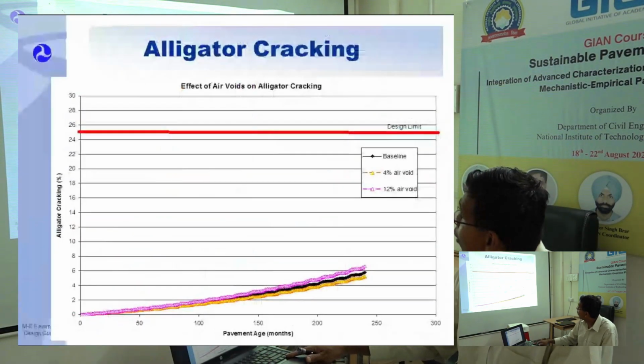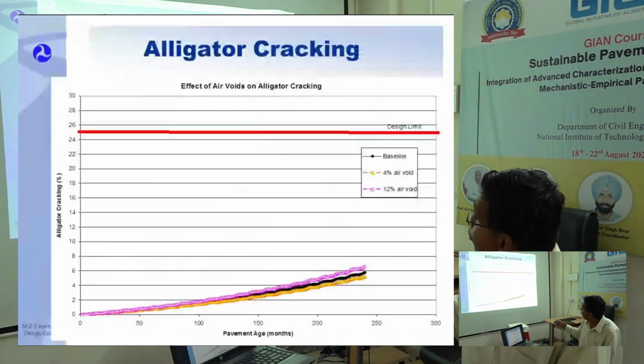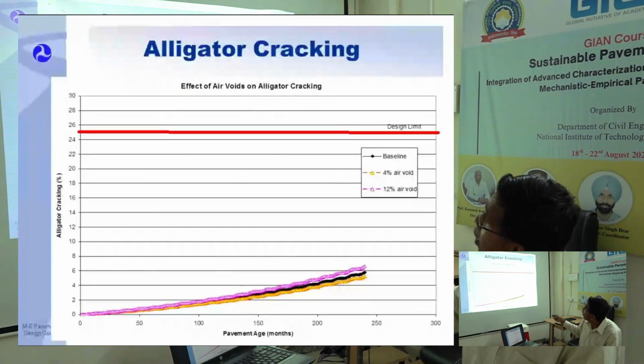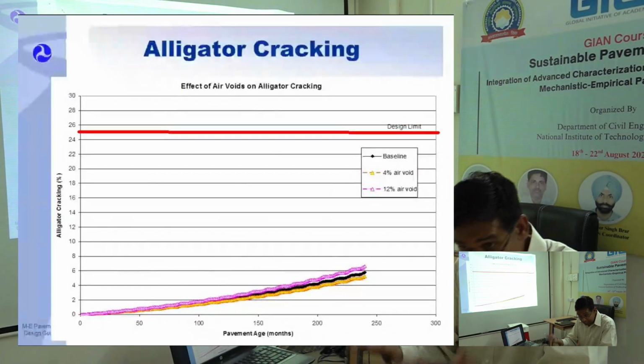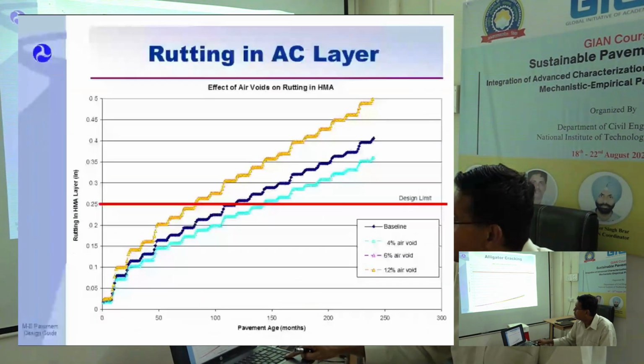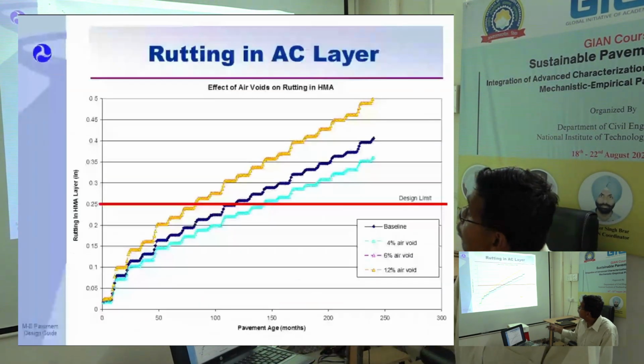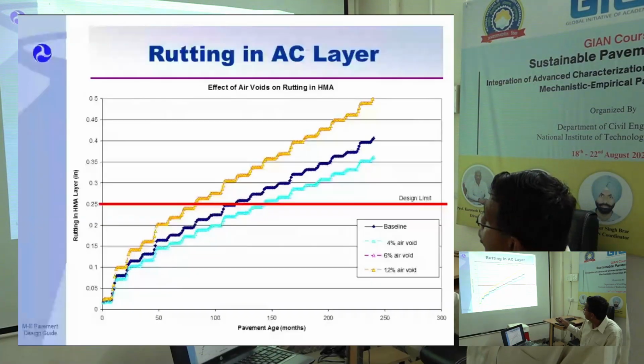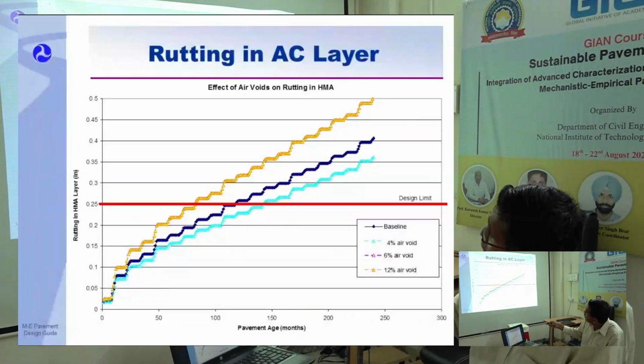Effect of air voids on alligator cracking, very minimal. 0, 4, 12, because it's a bottom-up cracking. It's from tensile strain at the bottom. Effect of air voids on rutting. You have baseline 4 and 6% and 12%, and you can see quarter-inch rutting right there. And you can see a big impact.